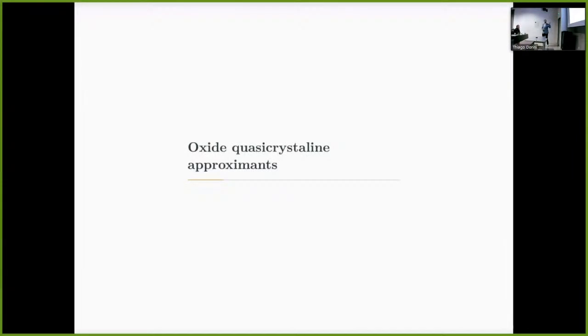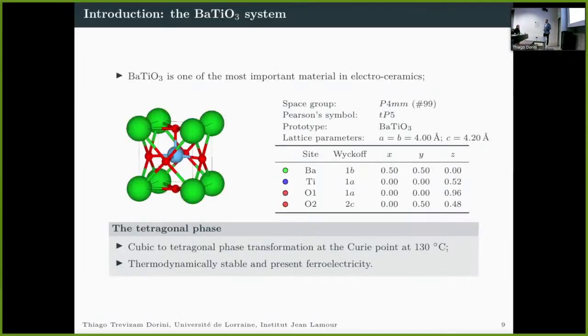Let's begin with the first part on oxide quasi-crystalline approximants. And I'd like to introduce how we discovered these oxide quasi-crystal materials. It began with the study of the barium titanate system. This is a very important phase, specifically for electroceramics. This phase has a tetragonal structure. And it's interesting to notice that it presents ferroelectricity, which is why this phase is so interesting to study. And of course, it's thermodynamically stable.